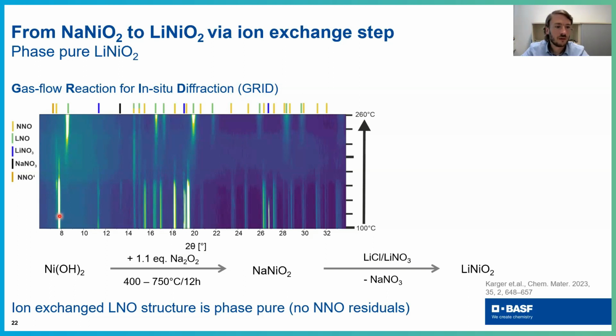And here you also see that the lithium nitrate reflex is losing its intensity, and there is a new reflex, which is sodium nitrate. So taken together, it means that there is sodium which is coming out of sodium nickel oxide, and there's lithium which is going in. So the ion exchange starts already at very low temperature, where everything is still kind of crystalline.